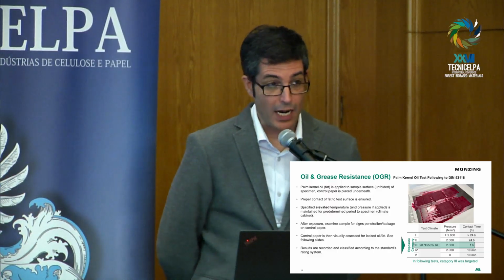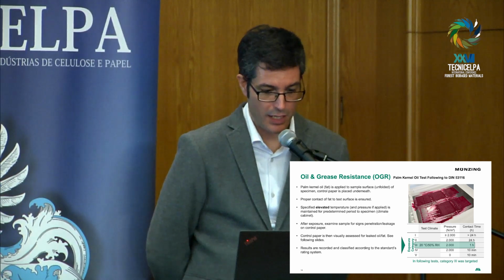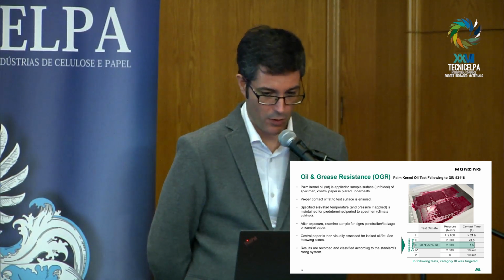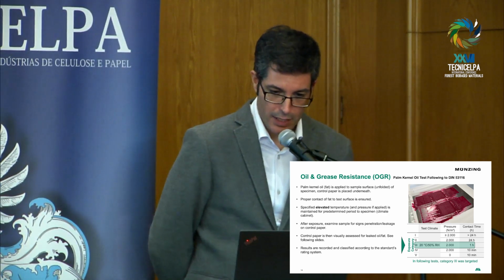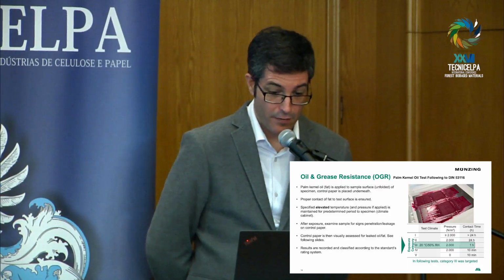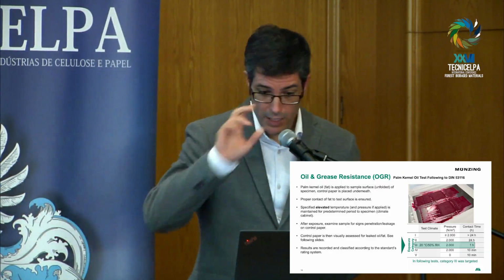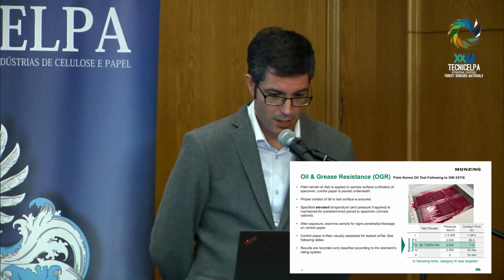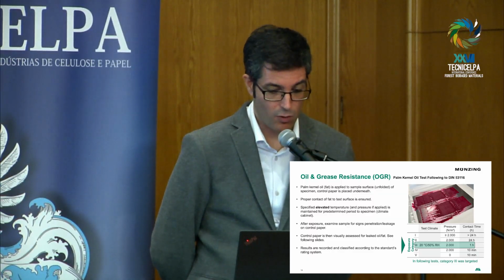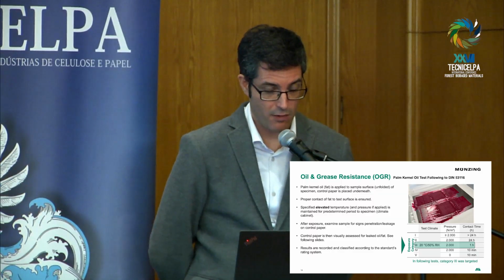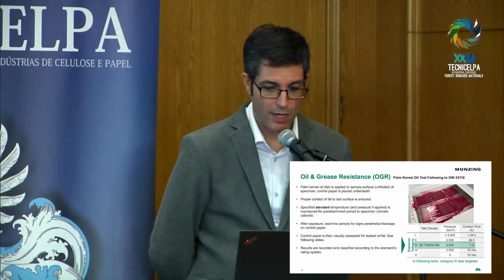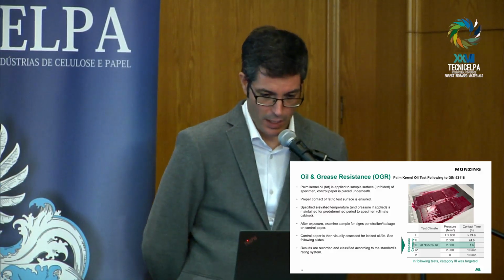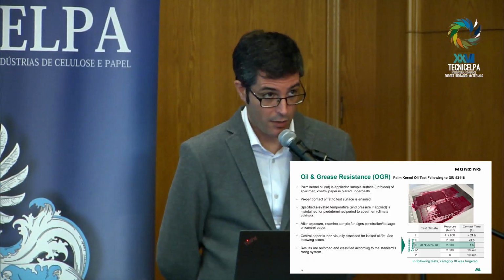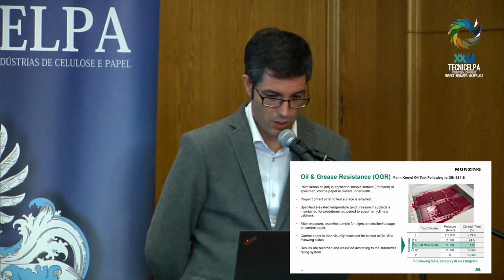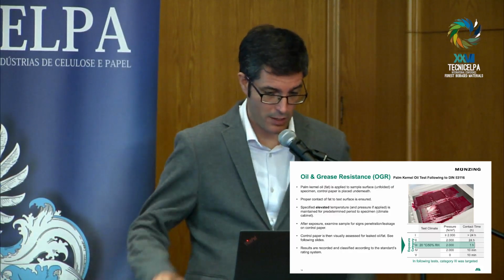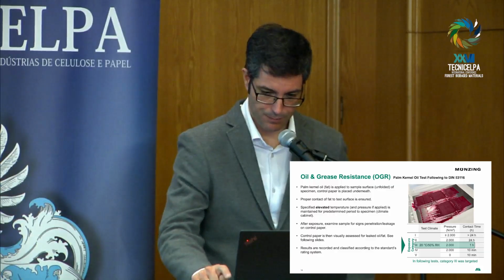After that, we analyze the penetration, the leakage on the control paper. This method gives us 5 different exposure categories. The climate conditions are always the same, 20 degrees and 50% relative humidity, but we can play around with the pressure and the contact time. In that case, we focus on category 3, which is 2 kilos and 1 hour contact time, to make this comparison test between all the samples.